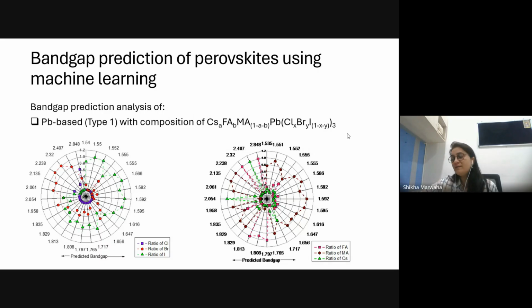We got this data set from research papers, and the 80-20 rule was used for training and testing the data, and quite good efficiency was obtained from this analysis. This study was done to determine the band gap in terms of the ratio of chlorine, bromine, and iodine, the ratio that I have discussed earlier. Then we checked the impact of one halide at a time by fixing the other, and saw the impact on band gap. Similarly, the impact of cations was checked, because one of the cations is already fixed. So we checked the A cation here. We varied the values of FA, MA, Cs, and then checked the combinations too, and saw the value of the band gap based on this.